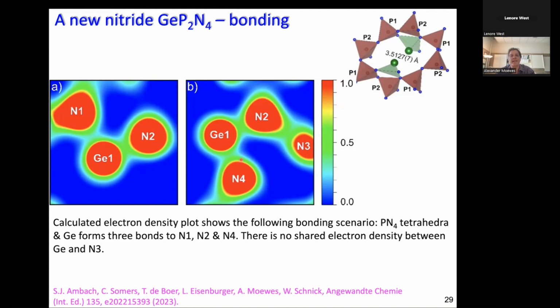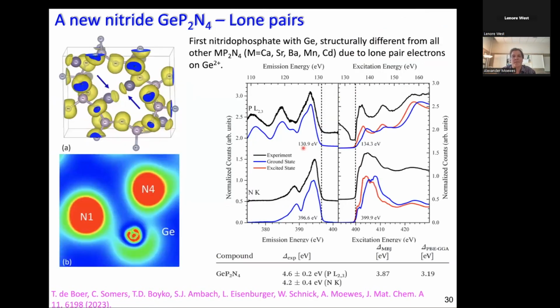So there is no shared electron density with N3, as you can see here, germanium and N3. So that was the first surprise that makes this somewhat unique. And the next surprise, which I show you here, was a nice demonstration of the relevance of lone pairs for the structure of this material, and that the lone pairs have a real impact on the structure.